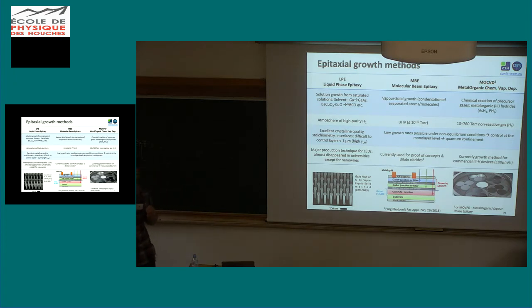The big problem with this technique is that it's very, very difficult to control the thickness of the layer you are growing because of the very high surface energy of this liquid metal. And nowadays, as far as I know, it's mainly used for the production of LEDs, and is also used by some groups, including us, for example, to grow catalyzed, in this case gallium catalyzed, gallium arsenide nanowires on top of silicon. I'll say something very shortly afterwards on this technology.